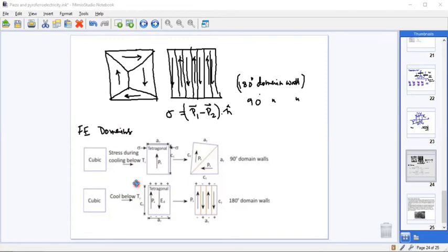For instance, the rhombohedral case of lead zirconate titanate, PZT, has the PS vector along the 111 direction, which gives 8 possible directions of spontaneous polarization with 180 degree, 71 degree, and 109 degree domain walls. On the other hand, a tetragonal perovskite structure, lead titanate PbTiO3, has PS along the 001 axis, and here domain walls are either 180 degree or 90 degree domain walls.